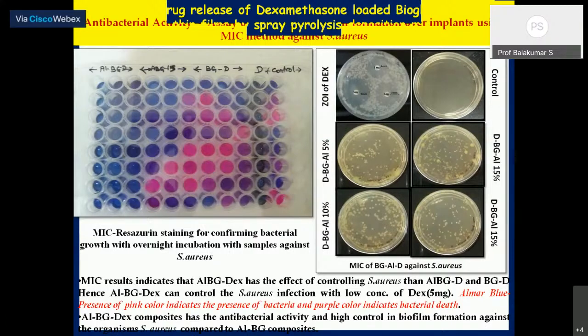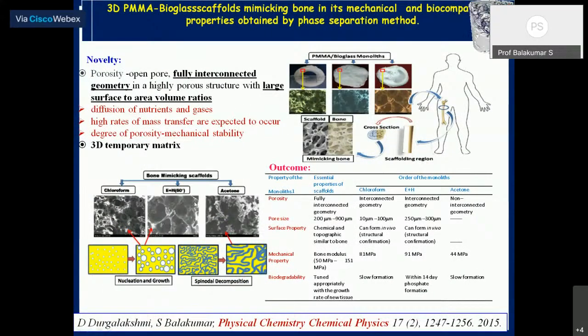So this was very simple. You can't imagine this porosity changes in the material just because of the solvent. We use three different types of solvent: chloroform, ethanol plus water, and acetone. If you look at this, the pore sizes change because of the solvent that we use. This is the structure with chloroform, this is ethanol plus water, then acetone. You can see that we can explain the material formation with spinodal decomposition. But property wise, if the porosity increases, absorption increases, degradation increases, and then biocompatibility increases.